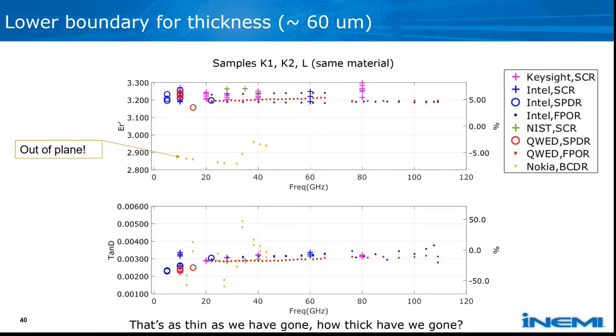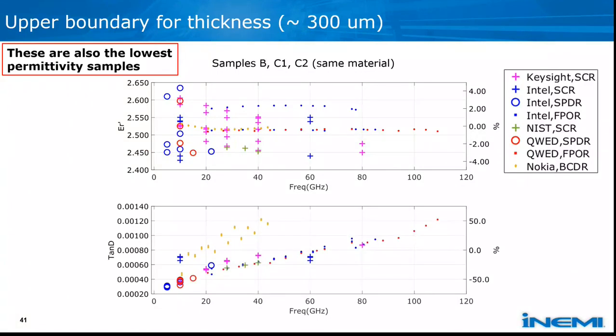So we've shown that we can measure really thin material pretty well. The upper boundary for thickness at about 300 microns is also, very conveniently, our lowest permittivity.